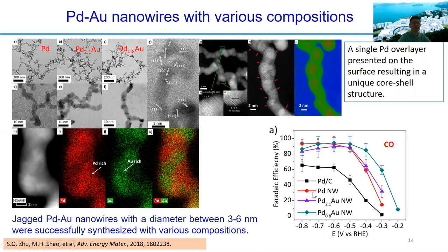But even for the palladium nanowire itself, the red one, you can see at the same high voltage, the activity of CO is much higher than the palladium nanoparticle. And with gold in it, we can see that the activity is even higher. More interestingly, the overpotential for CO2 reduction is shifted 100 millivolts more positively. So, a very nice catalyst compared to pure palladium.